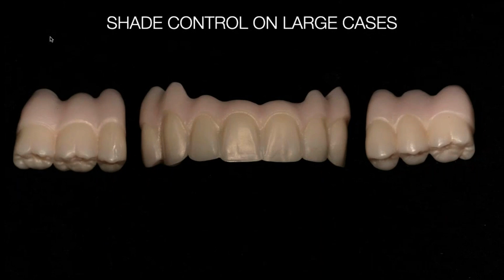I mean, I don't know if you've seen it or not, but I did a case where I had full contour molars and I had a bicuspid that had to have a veneering material because it showed, and the zirconia wasn't that nice looking. So we layered it, and when I fired it, I noticed the occlusal table on the single units on the premolar started to get lighter than the molars, and I'm like, what the heck did I do here? I just fired it, and of course, that was with the VM9, which was a 900 plus firing temperature. So I don't see it that much anymore, but I use both VM9 and Lumex, and they work beautiful